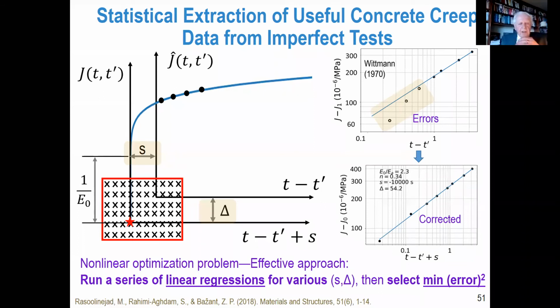So first we try to fit the power law to the initial data for 1 or 2 days. That was done by Rasoolinejad. It's a nonlinear problem. We used nonlinear optimization. It was running forever, very expensive computations, and did not always properly converge. Then we decided on a different approach, realizing that if the shift in strain, delta, is fixed, and the corresponding shift in time is also fixed, then the rest of fitting is a linear regression. A linear regression runs immediately.